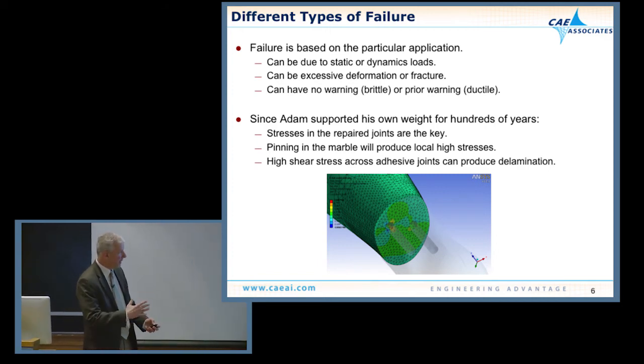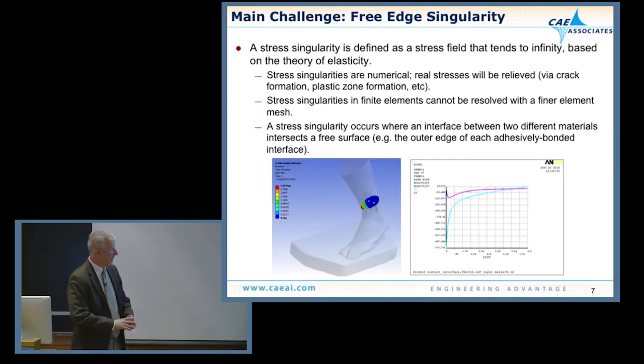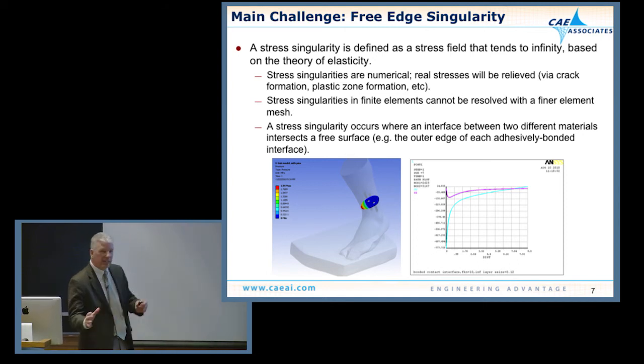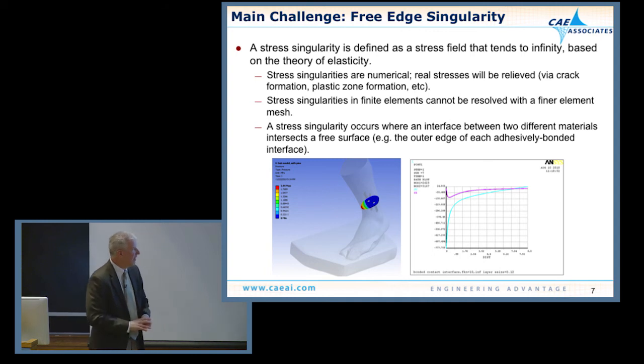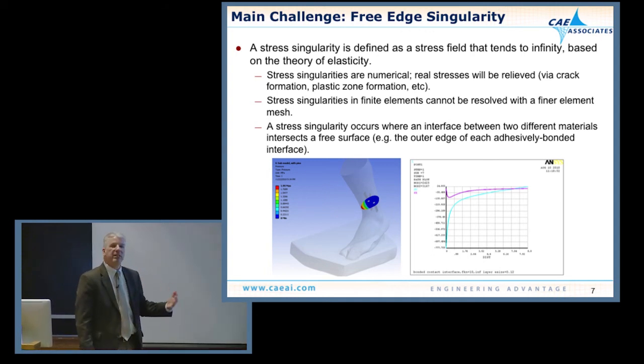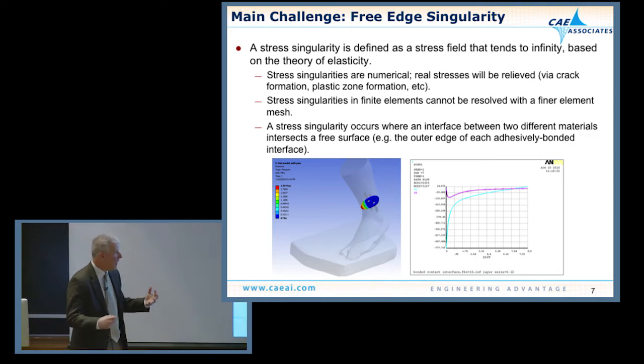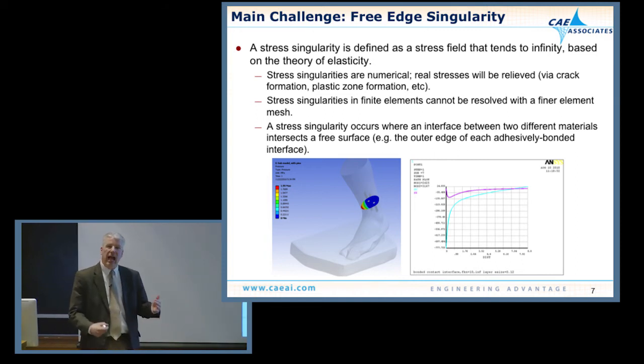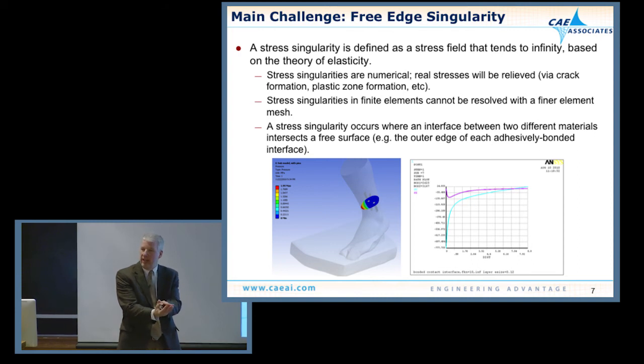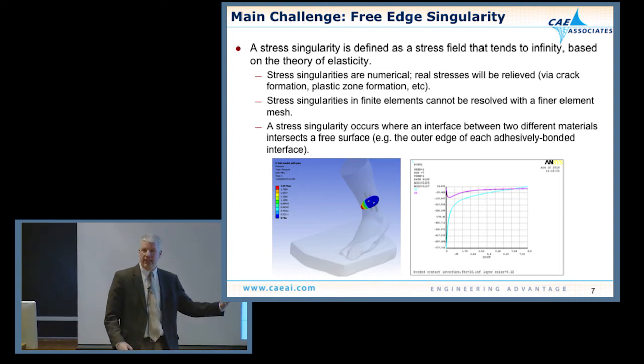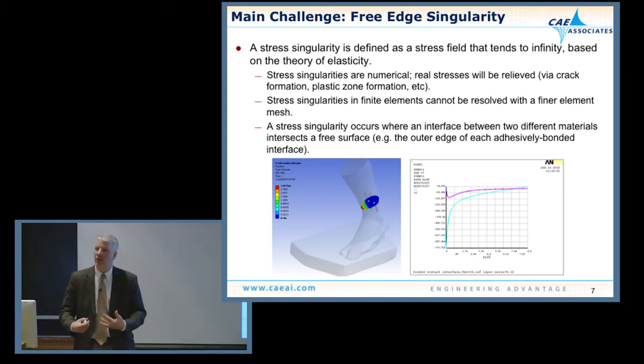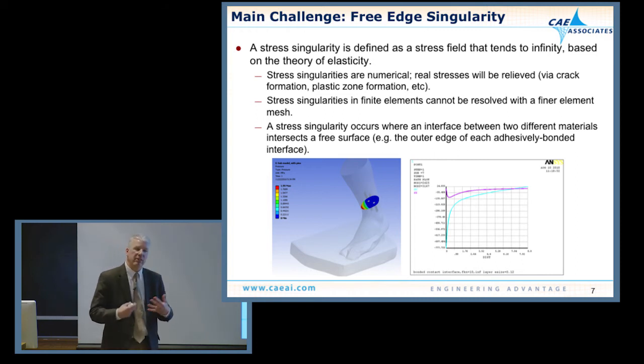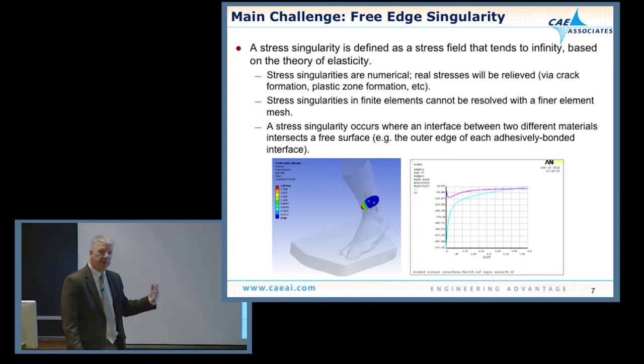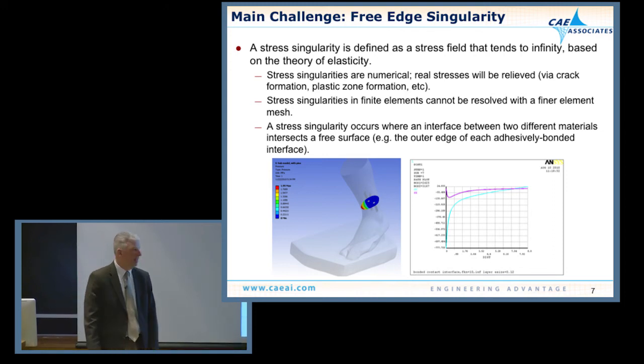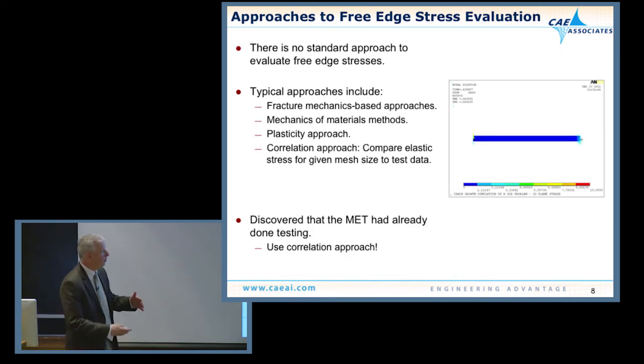And again, thus I was called in to take a look at the delamination parts to help Pat out, to tell him what the failure is. And just to give you another quick 15-second overview, the reason delamination is such a difficult thing to model is because when you look at the theory of elasticity and you predict stresses, at the free edge where you have an interface and you have a free edge where it meets the outside of the leg, the stresses that are predicted tend to infinity. That's called a stress singularity. Now, stress singularities aren't real. They're a consequence of the way we model things in the theory of elasticity and finite elements. But nonetheless, we have an infinite stress that we can predict, which isn't really going to help us because we know it's not infinite when it's going to fail. So we have to do something different.